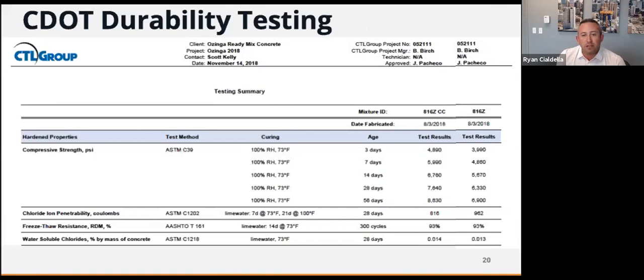So this is some actual local testing we did here in Chicago. CTL Group performed the tests as we proposed this technology to the Chicago Department of Transportation. Obviously, they wanted to see how well it worked, so we went through the variety of tests that they required. So we did compressive strength, chloride ion penetrability, freeze thaw, and water-soluble chloride ions. And as you can see, the strengths, there's the two mixes on the far right. The 816Z CC is the mix with CarbonCure, and the mix directly to the right is the one without.